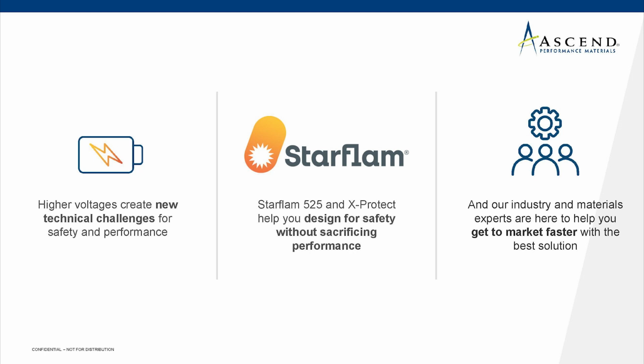That's a complex question. So we've seen the RTI data that Kim had presented, and that's essentially one of the main degradation mechanisms that we would see throughout an automotive lifetime, which is based on heat aging, which is actually what the RTI is rating. Keep in mind that RTI describes the temperature that degrades your properties down to 50% after an exposure of 20,000 hours.